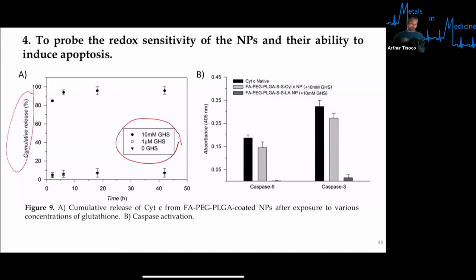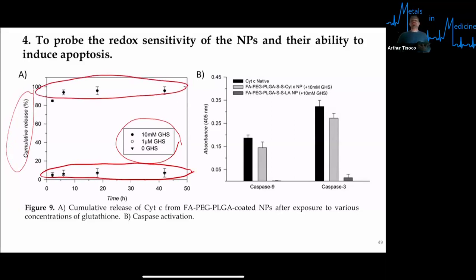And so we can see we have a low percentage of cytochrome C released in the low amount of glutathione, but a significant amount of cytochrome C released in the presence of 10 millimolar glutathione. So that indicates that the redox environment within the cellular environment should be sufficient to release the coating from the cytochrome C. But that doesn't mean that that protein is functional. That only means that you can release the protein. So what we're looking at to the right is the capacity of the protein to trigger activation of the caspases. Because remember, cytochrome C uses the caspases to induce apoptosis. So what we're looking at here is the activation of the caspases as a consequence of the cytochrome C.